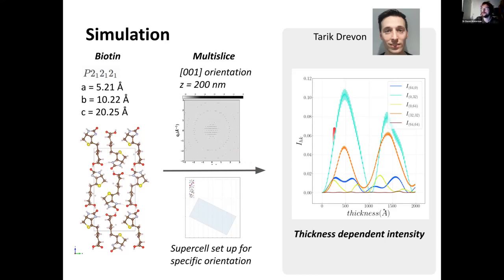And at the moment we can show certainly that you have quite dramatic effects on intensity with thickness going from full maxima at some thicknesses right down to complete extinction of certain reflections with different periods for each reflection so this is something that's understood in the dynamic theory of diffraction but it's obviously too perfect to fit to the real much subtle effects in the experiment.